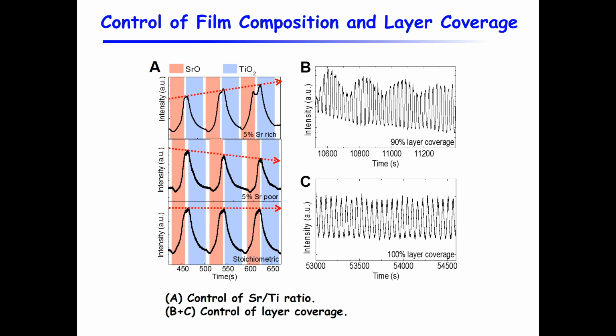And also, just imagine, even if you have the right ratio, if you are not covering the whole layer, or let's say you covered 90% and then you switch to another, when that happens, you will have this kind of beating. And if you have completely covered one layer and then go for the next layer, you have these stable oscillations in the RHEED intensity. So with this, let's say we have roughly 100 pulses for each atomic layer, so you can control it to a few percent.